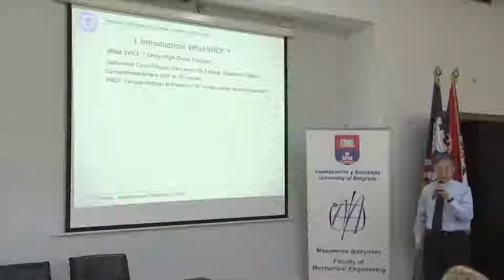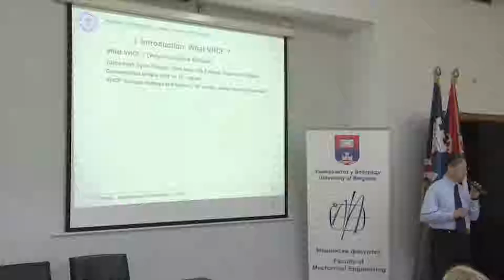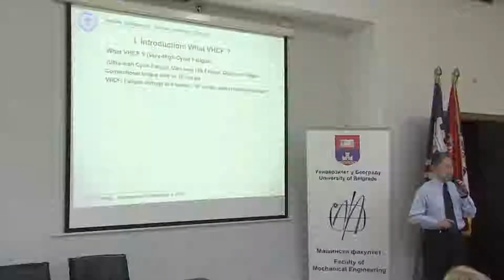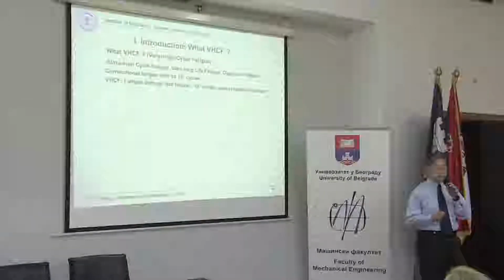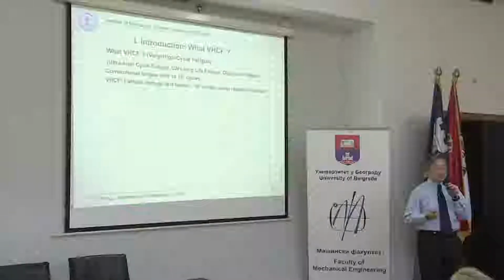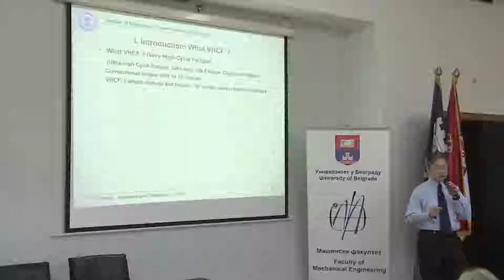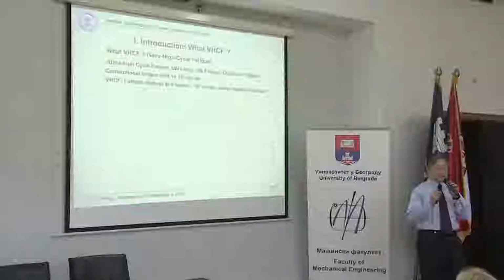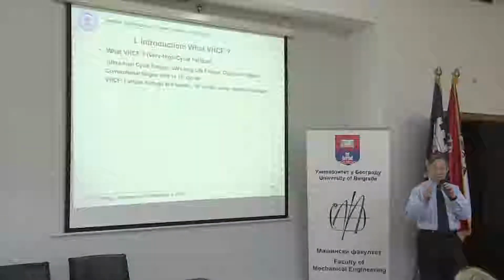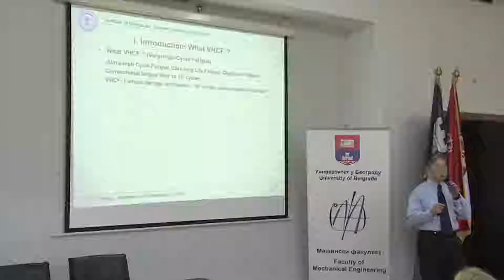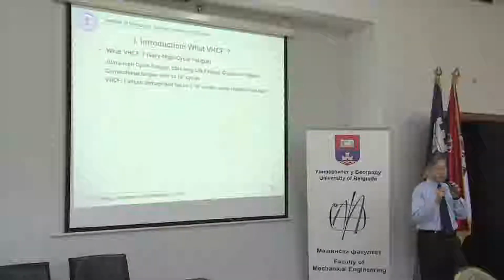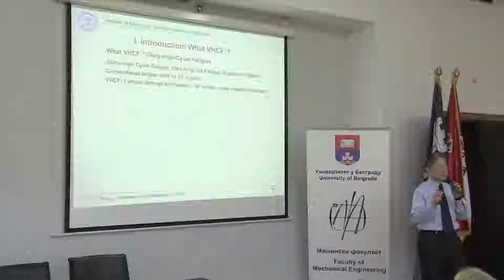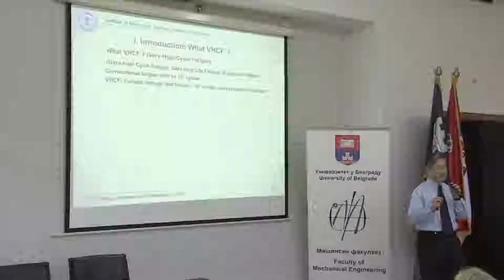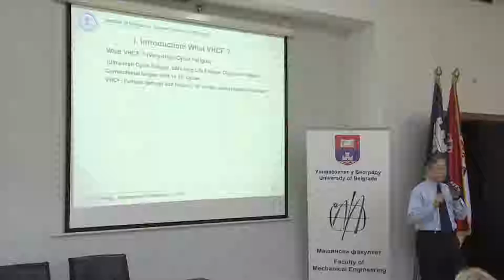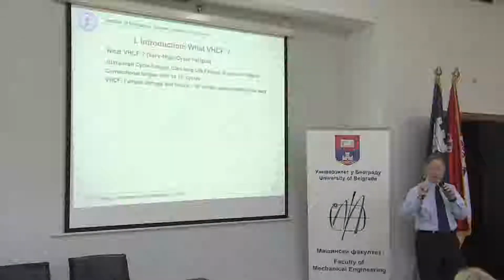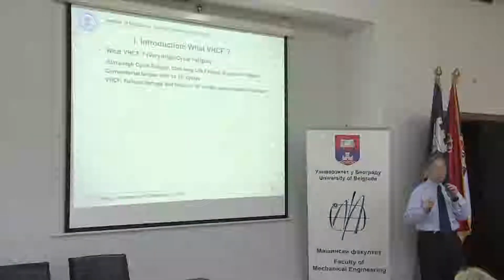Okay, first I will say something about very high cycle fatigue. Very quickly, very high cycle fatigue is a fatigue failure beyond 10^7 cycles of loading. Conventionally, the fatigue limit is regarded as the fatigue stress or fatigue strength at a loading cycle of 10 million. But in recent decades, people found that fatigue failure may even happen beyond this range, after 10^7 cycles of loading, after 10 million cycles of loading.